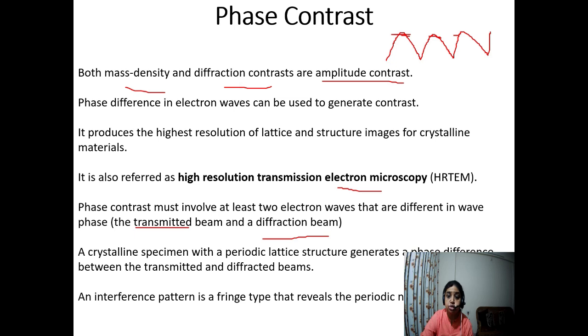At least you have the transmitted beam, then only with respect to that you can see the changes in the phase of the diffracted beam. This is a very important point. The phase change in the diffracted beam should be measured with respect to the transmitted beam. So it is a must to take two beams. That is a bright field. So it is a must to involve at least 2 electron waves that are different in wave phase. If it is being diffracted, then definitely its phase will change, and it will have information about from which crystal plane it is being diffracted.